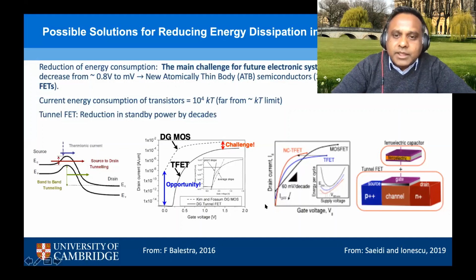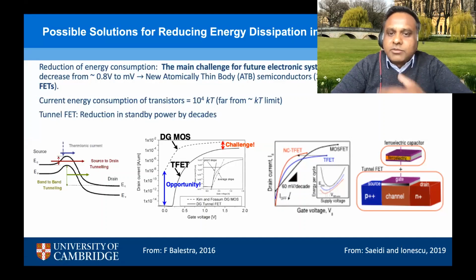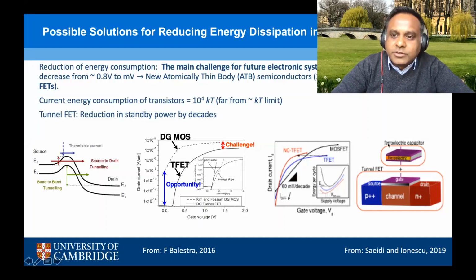So one thing the community is looking at is to realize these tunnel FETs, which give us this low off-state current, but integrate them with this negative capacitance gate dielectric. If we put a ferroelectric in series with the gate dielectric, we can achieve what's called negative capacitance, which provides a boost or amplification in voltage due to the polarization in the ferroelectric. And that enhances band-to-band tunneling and gives rise to slightly higher current than one would get in a regular TFET. And if we look at these curves, we can see that at a given operating voltage, we can actually reduce the voltage for a tunnel FET while achieving the same current as one would get in a MOSFET.